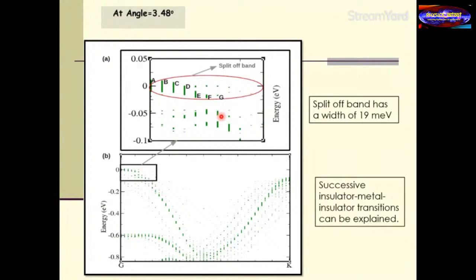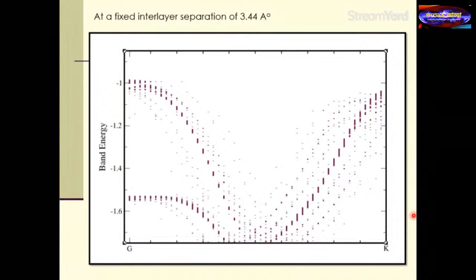So therefore what we can show is that we can explain the experimental observation of successive insulator-metal-insulator transitions seen in this material, and it's not because of the undulations in the structure. But I spoke about that in some regions the separation was nearly 3.8, and in some other regions it was 3.2. It's not because of that, because even if we kept it fixed at something intermediate between these two values, what we found was that you do have this kind of split-off band forming over here. So what's the origin of this?